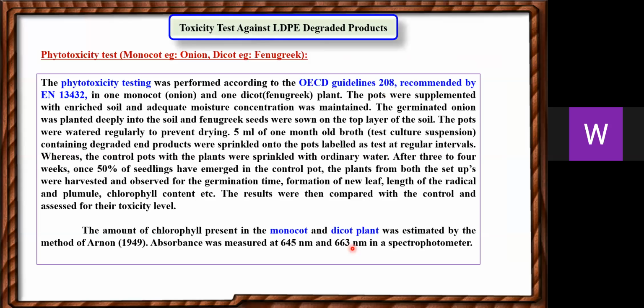Toxicity test against LDPE degraded products. Phytotoxicity test was performed according to OECD guideline 208, recommended by EN 13432, in one monocot plant and one dicot plant. After 3 to 4 weeks, the plants were harvested and observed for germination time, formation of new leaf, length of the radicle and plumule, and chlorophyll content, and the results were compared with the control and assessed for the toxicity level. The amount of chlorophyll present in the monocot and dicot was estimated by the method of Arnon, and absorbance was measured in the spectrophotometer.